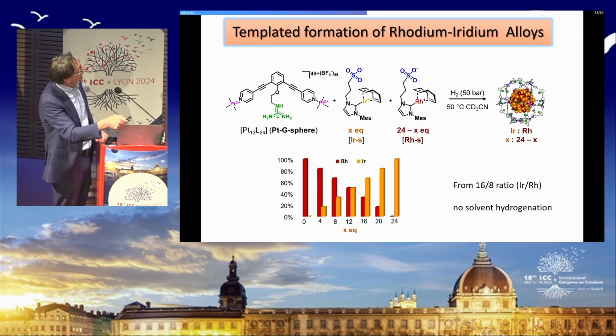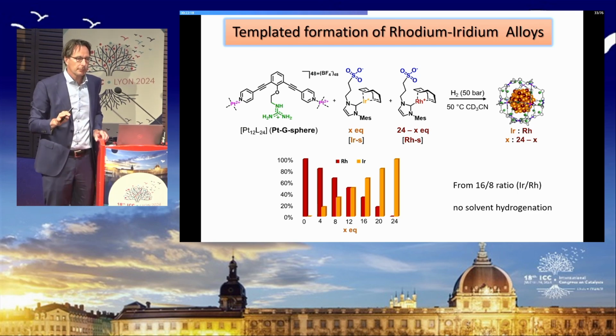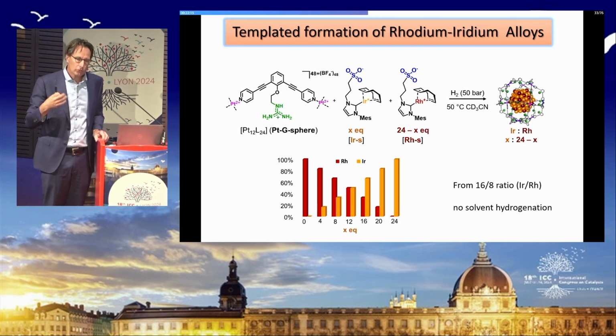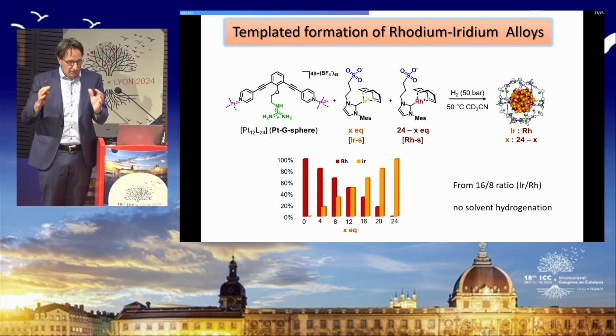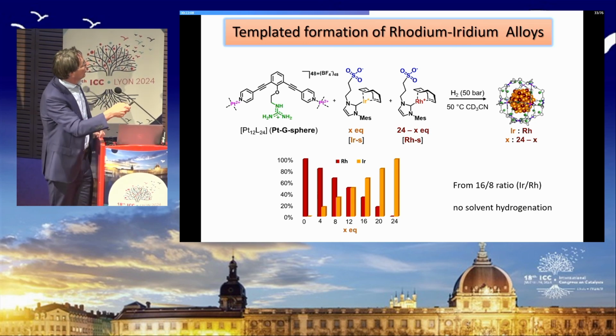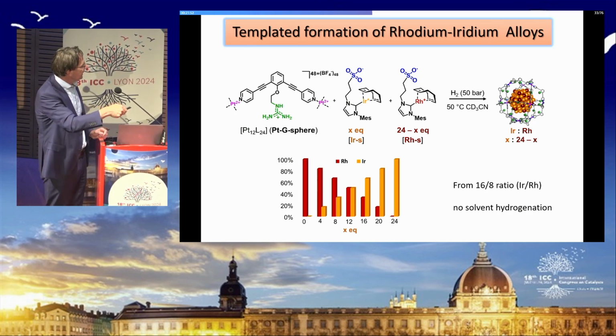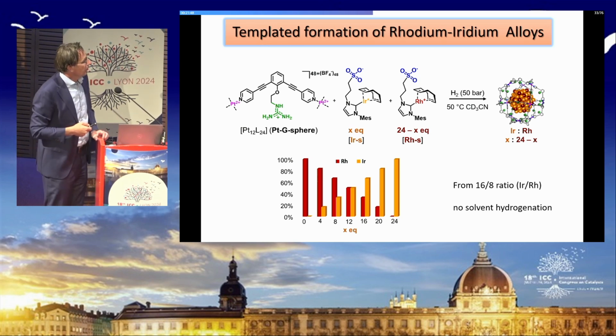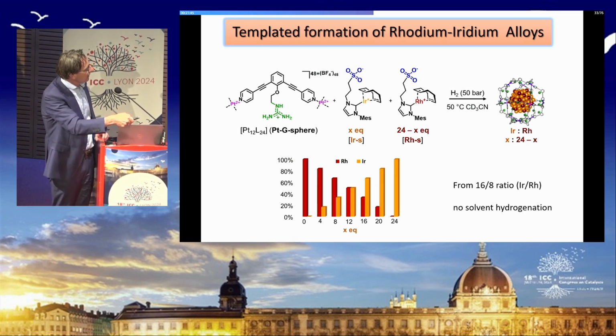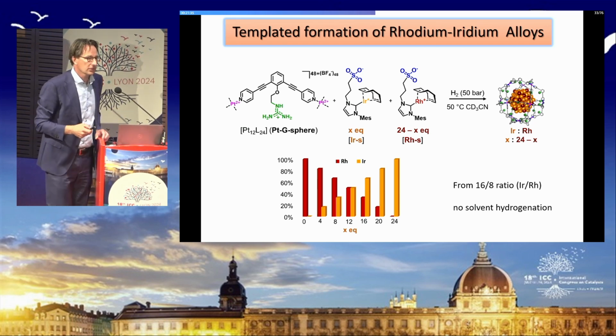So then we thought maybe we can make rhodium-iridium alloys to tame a little bit the reactivity of the rhodium nanoparticle, but also to demonstrate that we can use our nano-sized cage to make alloys. So what we did is we took again our platinum cage with the guanidinium, and now we mix in an iridium complex with the sulfonate and the rhodium complex with the sulfonate, mix them in different ratios and do the hydrogenation, expecting to form the alloy. And we did these different ratios. And what we found from these experiments is that if the ratio is 16:8 or higher, with a larger content of iridium, the activity is tamed to such an extent that we no longer see solvent hydrogenation.